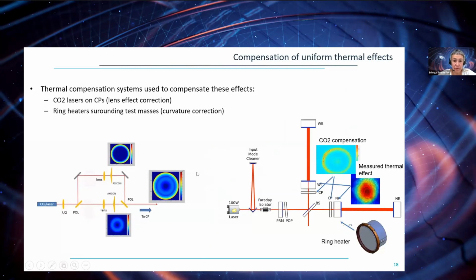As I said, we correct for those thermal effects. So we have what we call the thermal compensation system, which are CO2 lasers, which will correct for the lens effect inside the input mirror, which is due to the absorption. In front of them, we have compensating plates on which we shine those CO2 lasers, with a kind of donut shape, in order to have the opposite lens effect.